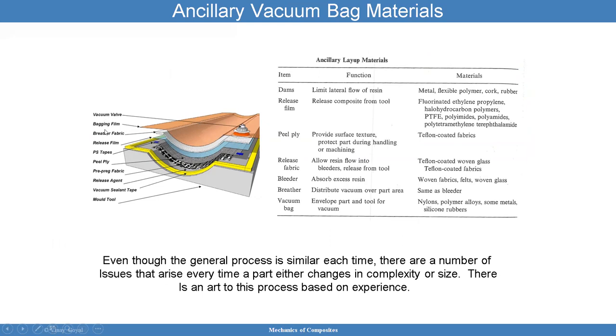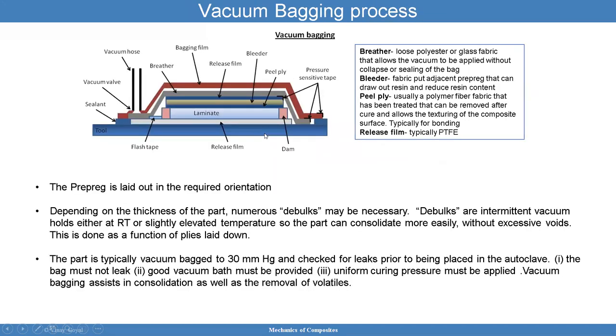On the left side, I show the vacuum valve, the bagging film, the breather fabric, the release film, the tapes, peel ply, prepreg fabric, release agent, vacuum sealing tape, you can see it in yellow there, and mold tool. So you have dams, and what is the purpose of dams? The dams are useful for limiting lateral flow of resin. So let me show you. You see this is pointed as dam here in pink. If I have this laminate, the resin could flow out on the edges, on the lateral sides. We can prevent that by using a dam.